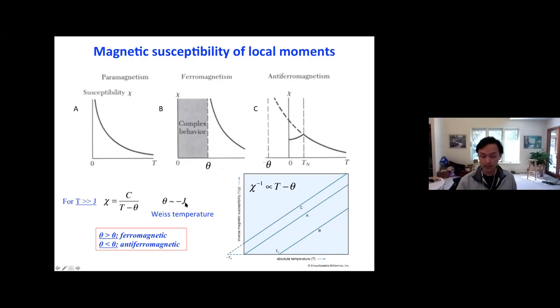So if the system is ferromagnetic, the localized spins interact with each other ferromagnetically, and you will expect the Curie-Weiss law to diverge at a positive Curie-Weiss temperature. And if you plot 1 over chi, it shows a linear dependence, and the TC here, or the Curie-Weiss temperature, is positive for a ferromagnetic system. For an anti-ferromagnetic system, the Curie-Weiss temperature is negative, and if you plot 1 over chi, there will be a negative intercept, a negative temperature here. Okay. So if you can measure the temperature dependent susceptibility of the system, that's one of the best ways to really show the presence of local moments in the system.